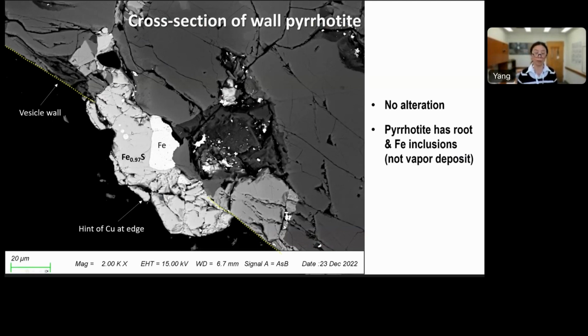So several things to note here. We don't really see alteration of the pyrrhotite grain in the cross-section. There are cracks and fractures which are possibly generated during sample preparation. We do have a hint of enriched copper when we put our electron beam at the edge of this pyrrhotite grain. And the pyrrhotite grain is actually not just sitting on the vesicle wall. There are roots of the iron sulfide grain, irregularly shaped, going into the rock. Although the outside profile looks very unusual, we do see things extruding into the rock. And it also has a lot of iron metal grains. And the iron metal grains help us to understand the formation of the iron sulfide as well.